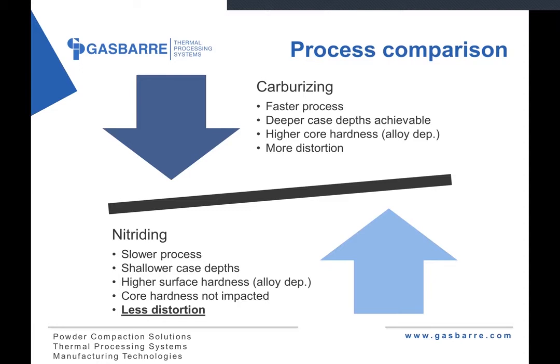Not to say there's no distortion — anytime you put heat to a piece of metal, you're going to relieve some prior residual stresses and get a chance of creating some distortion. But comparing two different parts, you would expect a nitrided part to have significantly less distortion, to the point where you can usually eliminate some post-heat-treat processing — maybe instead of having to face a gear to machine it back to size, you can use the gear as-is after nitriding right out of the furnace.